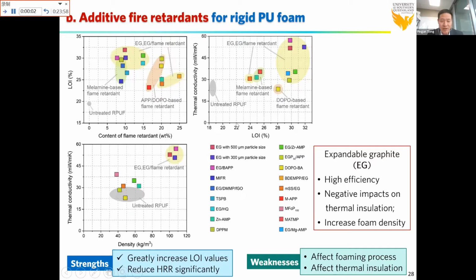But for additive fire retardants, basically you look at this. If you get a V0 rating, you just need a relatively lower content, about 10%. But you can get a high LOI value. At the moment, expandable graphite is a highly efficient flame retardant for PU foam. But the problem is it can have a negative impact on the thermal insulation, because you can see increased thermal conductivity, and it also increases the density. So that can also affect the foaming process and the thermal insulation as well.